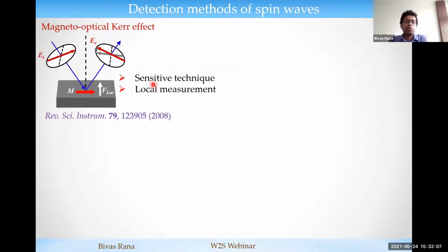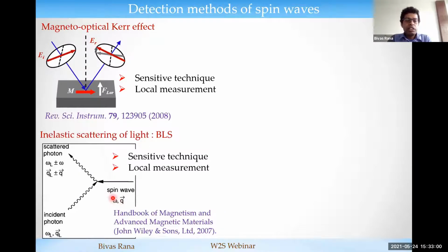So the first one is the magneto-optical Kerr effect. Professor Vedanto's group is actively using this for understanding domain wall dynamics. So basically, this is a very nice and very sensitive technique to measure the domain wall or the spin wave dynamics. You send a linearly polarized laser beam, and upon the reflection, the plane of polarization is rotated due to the interaction with the magnetization of the system, and the angle of the rotation is proportional to the change of the magnetization. That means the amplitude of the spin wave, and that's how you can measure the spin wave amplitude in a very sensitive manner.